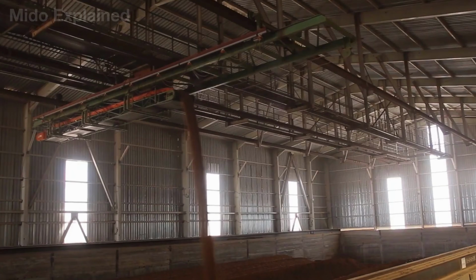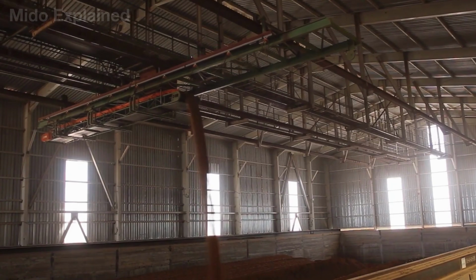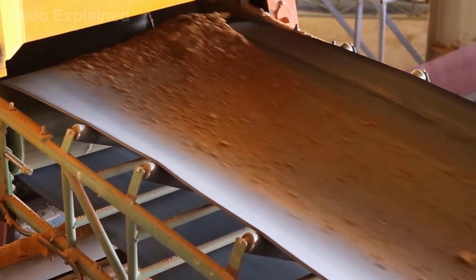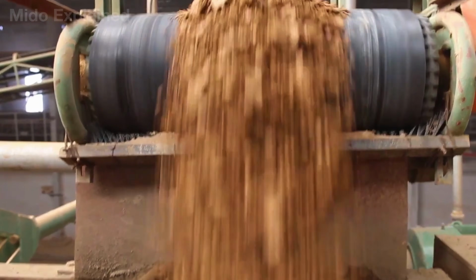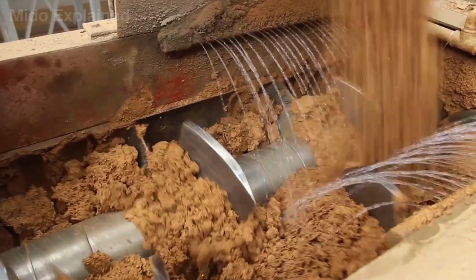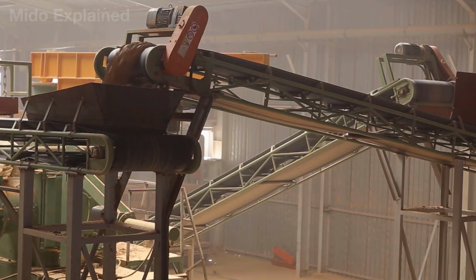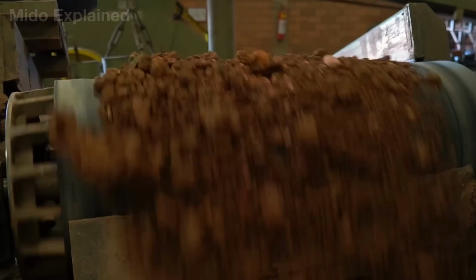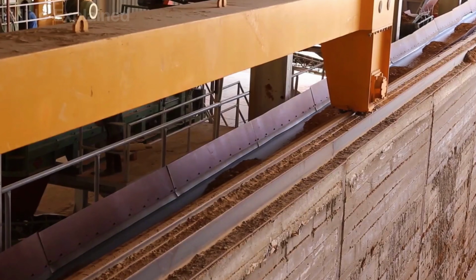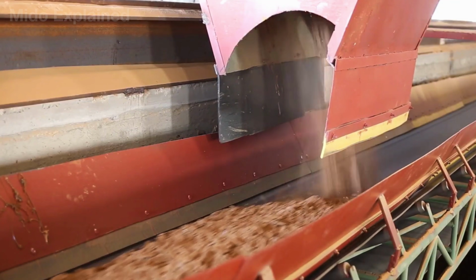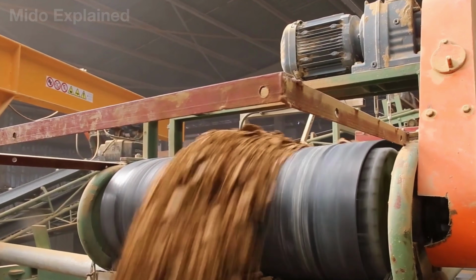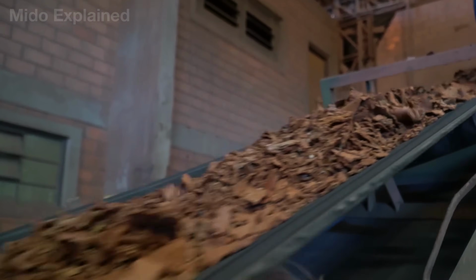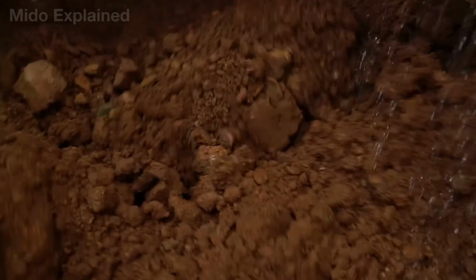Before it can be shaped, the clay must first be crushed to break up large lumps and remove any remaining impurities. It then passes through a series of roller crushers that reduce it to a more uniform size, ensuring a stable forming process later on. Finally, the clay enters a mixer, where a carefully controlled amount of water is added to create the right level of plasticity. Even a difference of just a few percent in moisture content can cause the clay to crack during drying or deform during forming, making the entire batch of bricks fail quality standards.